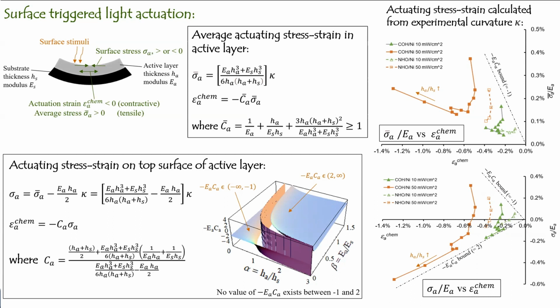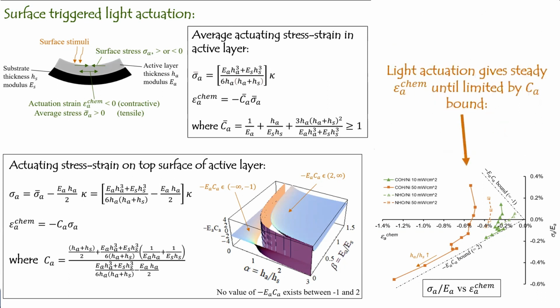Okay. And then when you plug in the experimental data, you measure the curvature, kappa, you calculate the stress and the strain, and you plot them out. Now you see that basically, at least for quite a large range, the behavior is constant strain, no longer constant stress. So quite interesting. Electrochemical actuation, constant stress, but light actuation, constant strain. Quite interesting. So light actuation gives steady actuating strain until it is limited by that bound, right? So it goes from here and then bends towards the bound. Okay.